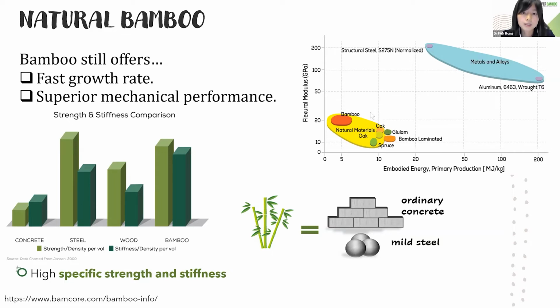But when we do the bending test of these structures, we can see that the bamboo laminated ones have a higher mechanical strength, but for the bending modulus, it is lower than some other materials. In addition, all of these are natural cellular materials. But compared to metals, we found the metal has a super high flexural modulus and super high flexural strength compared to our natural materials, which are not comparable.